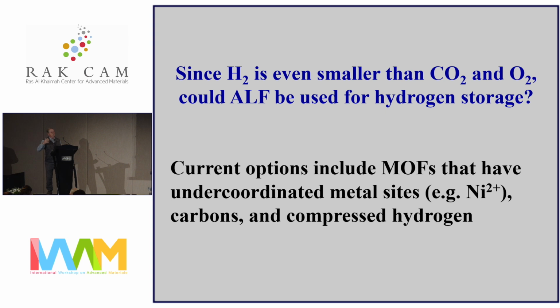So the other obvious molecule to absorb would be hydrogen, because that's smaller than CO2 and oxygen. And so could we use it for hydrogen storage? And as Mohammed mentioned, there's a huge amount of interest in hydrogen storage, and it's a problem for any future hydrogen economy. So people use MOFs, but they focus on MOFs with under-coordinated metal sites, which Jeff Long, for example, has done a lot of work on, where the hydrogen will bind to, say, nickel or a metal of that type. People use carbons, but carbons, especially if there's a separation involved, are not great, but they're cheap.